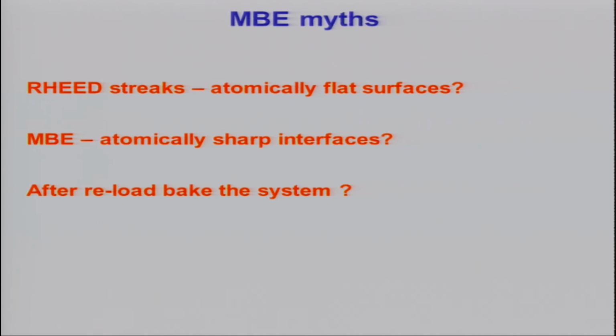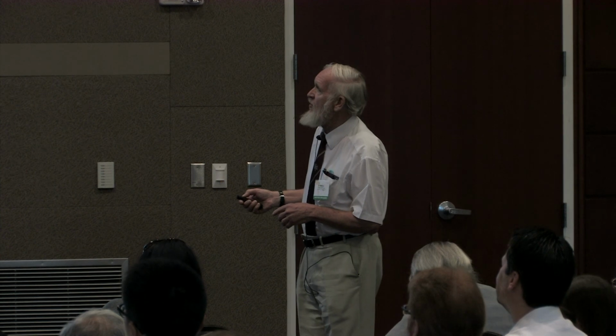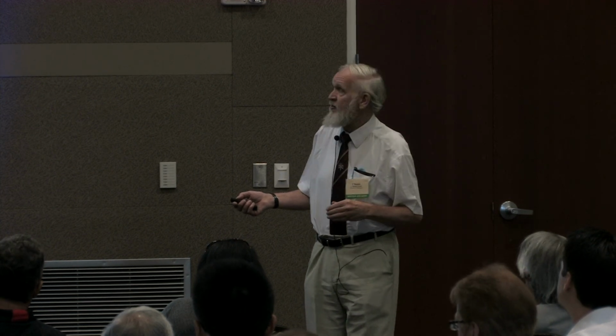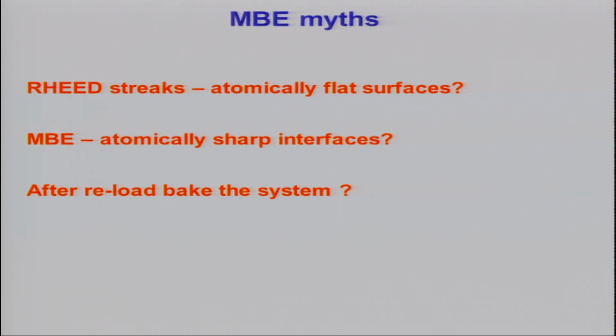Several myths that I want to discuss finally. Okay, we heard earlier about RHEED streaks from Al, and it's become in the literature, it's nothing to do with Al. Al didn't make this mistake at all, so I'm not blaming him for this. You see repeated over and over again that RHEED streaks correspond to atomically flat surfaces. It's complete and utter nonsense. Okay? The RHEED streak occurs as a result of disorder on the surface. Okay? You can see this very easily if you look at a really perfect surface, as Al correctly said. The Ewald sphere cuts the reciprocal lattice rods in sharp points. If anybody ever wants to see an example of a really good RHEED pattern, look at a silicon 7x7 surface. It's really a whole series of arcs with sharp spots. An atomically flat surface will not give you a RHEED streak at all. Okay, so that's the first thing.